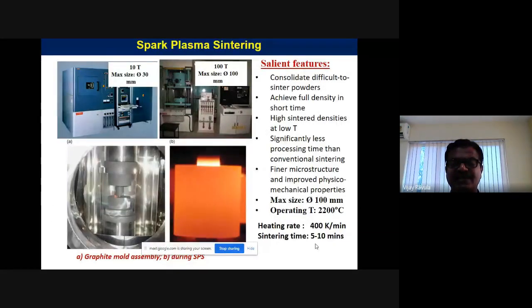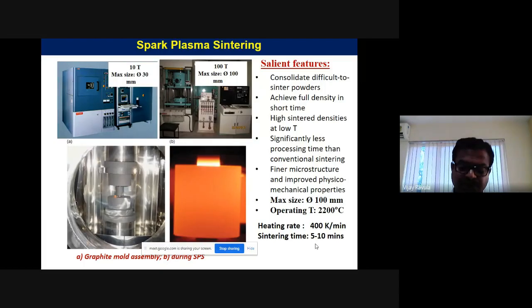Coming to another advanced processing, as you said, when you make nano powder and do consolidation from the powder, conventionally it is press and sinter. But when the nano powder is exposed for longer times in the conventional sintering process, after coming out of the furnace it no longer remains nano sized or a nano grain structure. It becomes a conventional polycrystalline material, and there is no advantage of using nano powders to make a component by the conventional process. Longer exposure at higher temperatures causes grain growth, and then it becomes like any other conventional material.